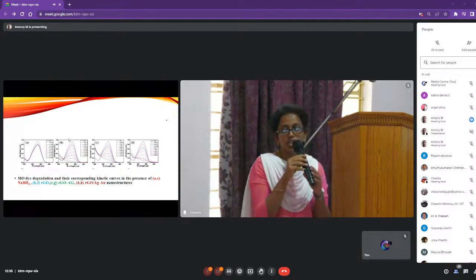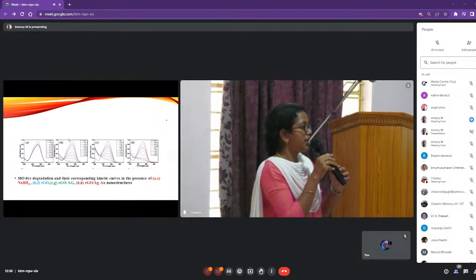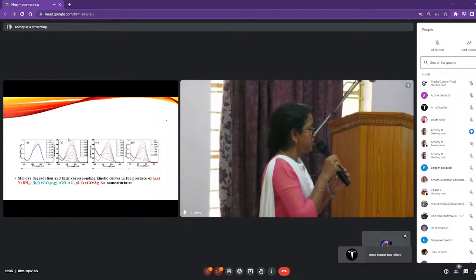Similarly, for methyl orange, the degradation takes place in the same way by adding NaBH4. The degradation takes place over 90 minutes, and reduced graphene oxide takes 35 minutes. For reduced graphene oxide-Ag, it takes 20 minutes, and reduced graphene oxide-AgAu takes 5 minutes for the degradation process. So from this we confirm